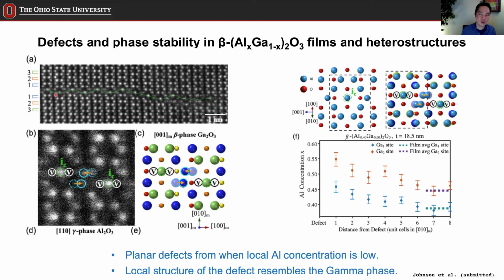in question, right? So what we found out by doing the quantitative STEM analysis was that this formation is in fact directly related to the local aluminum concentration. Now what we did was we exactly figured out the structure within the line of defect, which is explained here. And another thing is by looking at the column intensity, we figured out the local aluminum concentration, and that plot is shown here. So now the x-axis here is the distance from the defect, right? So this is a defect, and that's the distance from the defect, either going up or down. It's all combined. And then this is the aluminum concentration.